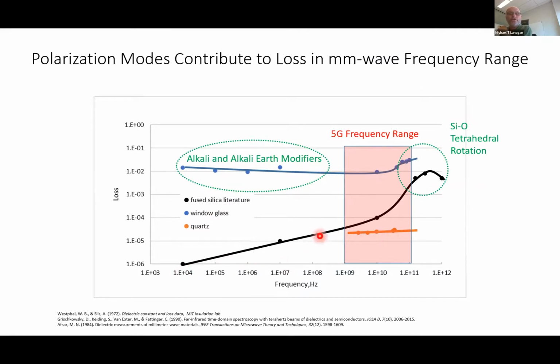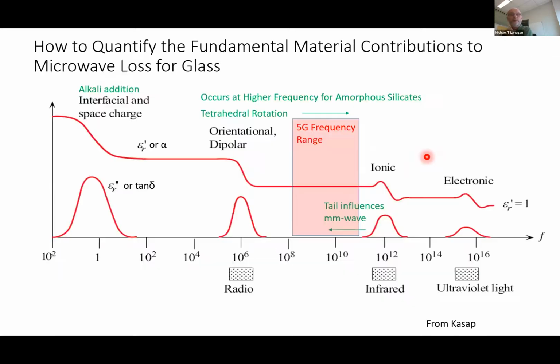Here is the pure silica. So again, the same composition between the quartz and fused silica. But as we start adding these modifiers, we see their contributions even at lower frequency in terms of the loss. And then as we get to higher frequencies, we're just starting to see this contribution of the silicon oxide here. And I would love to get to higher frequencies to see where this will roll off, and we can understand perhaps the contributions a little bit better of these silicon oxide and tetrahedral rotations.